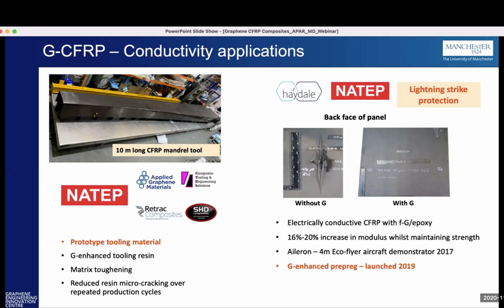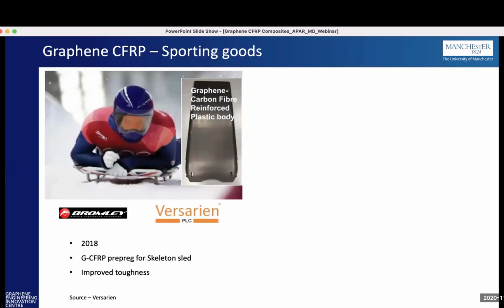But also on the back of that, like I mentioned earlier about multifunctionality, they actually managed to increase the modulus in the material as well. So increase that by 16 to 20%. And this material has actually been in an aircraft demonstrator in 2017. So that was a very successful demonstration. And this material is now actually available in the market. You can actually buy this. It's commercially available.